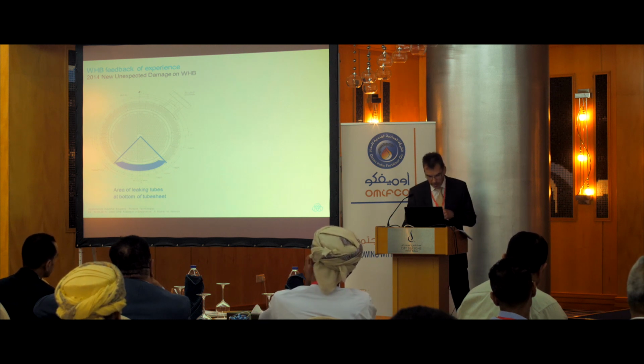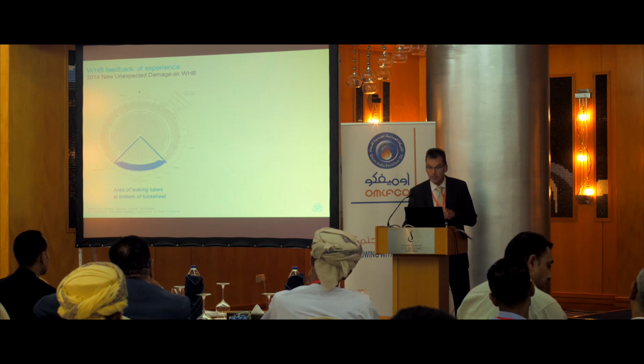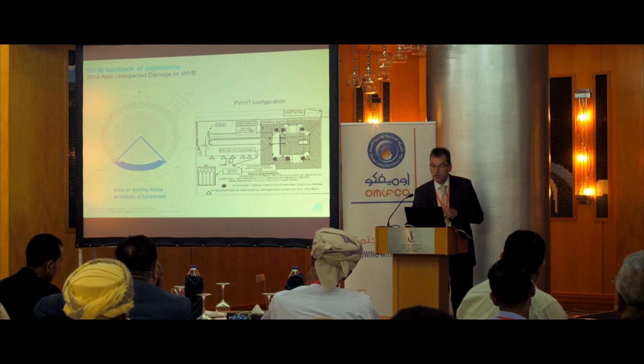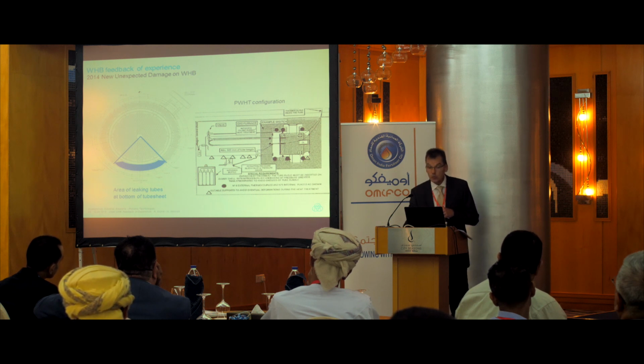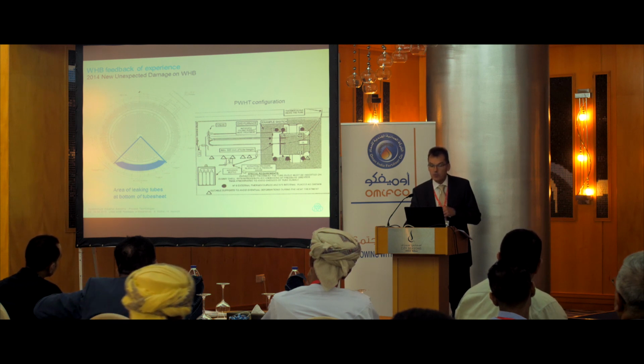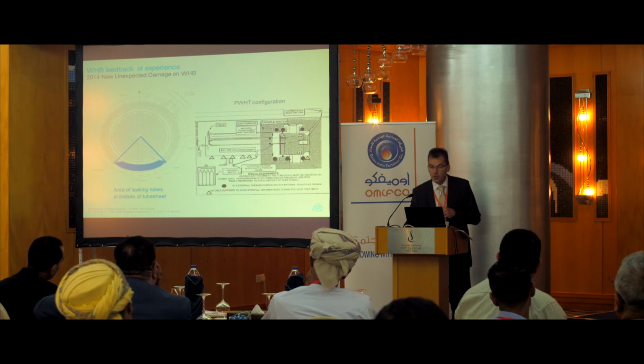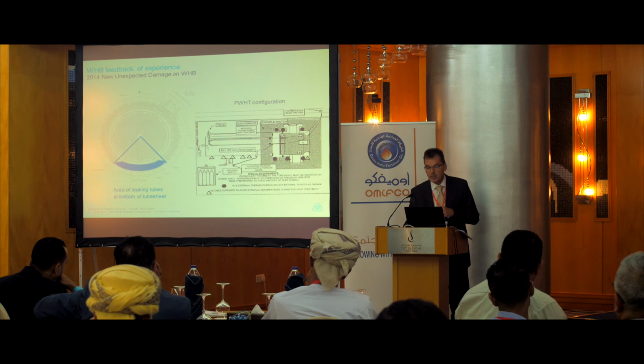During the root cause meetings at the manufacturers, we were informed that during the post-weld heat treatment, cracks had been experienced in the seal weld of the auxiliary shell. That means the shell is welded up here to the tube sheet and there had been a crack, and what did they do? Of course, they fed in nitrogen. And the nitrogen was not warm, it was cool nitrogen from the bottles. Our assumption at this time was that this affected the lower part of this auxiliary shell near the tube sheet, the post-weld heat treatment of the tube-to-tube sheet.